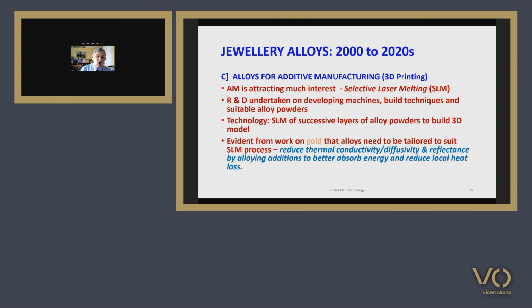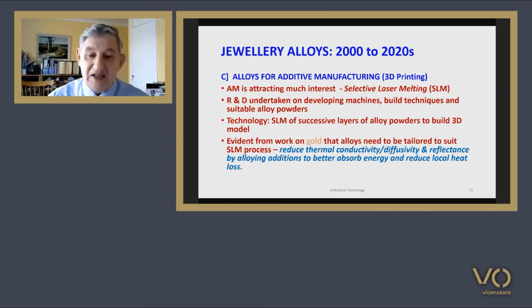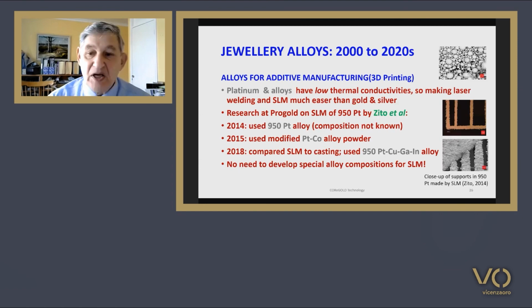It was very evident from the work that was done on gold for additive manufacturing that alloys need to be tailored to suit the selective laser melting process. You need to reduce the thermal conductivity and diffusivity and reduce the reflectance by adding alloying additions that better absorb energy and reduce local heat loss. This is because gold and silver have high thermal conductivities, and their high reflectance means that the energy tends to bounce off the surface rather than get absorbed. However, platinum and its alloys have much lower thermal conductivities, making laser welding and selective laser melting much easier